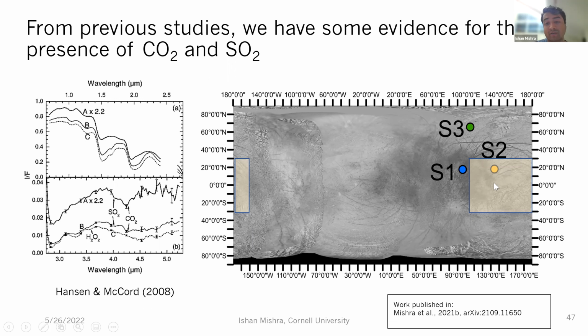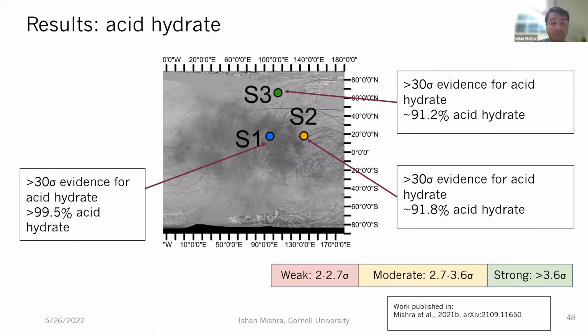So there were significant parts of the trailing hemisphere where they found carbon dioxide and weakly sulfur dioxide. So what were our results? Firstly, and this was the most expected one, there was a very high detection significance for acid hydrate. In all 3 spectra, we found that acid hydrate was strongly present. And in S1, which was coming from the darkest parts out of the 3, acid hydrate dominated completely, greater than 99.5% abundance, slightly lesser in the other 2.